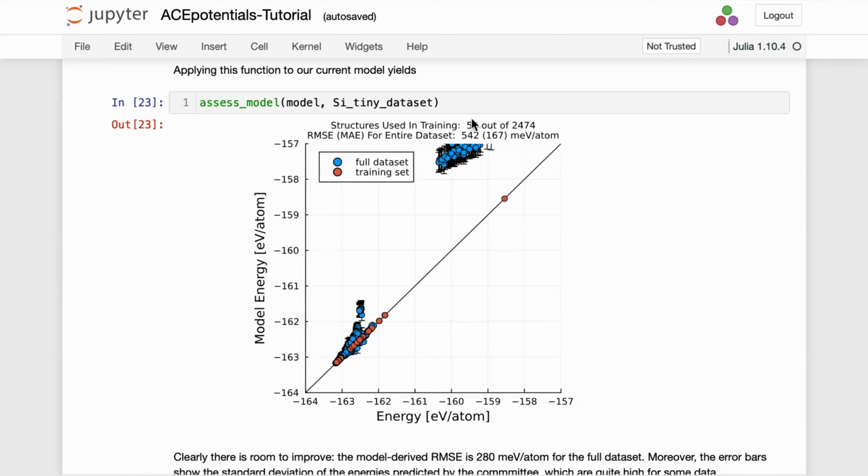Yeah, so completely agree. If I can reframe your question, you're almost saying, why don't these error bars cover the true? Well, I would say that's maybe not even a problem if you're just gonna chase large uncertainty regions. Probably the thing you would care about more is, are the largest uncertainty ones also the ones that tend to have the largest errors? I think what I can say is that the type of active learning that we described, where you just look for uncertain predictions and iteratively add to the training set, seems to work very well in practice. But there's a lot still to be understood about how to maybe rescale some of these uncertainties using conformal prediction or other things.